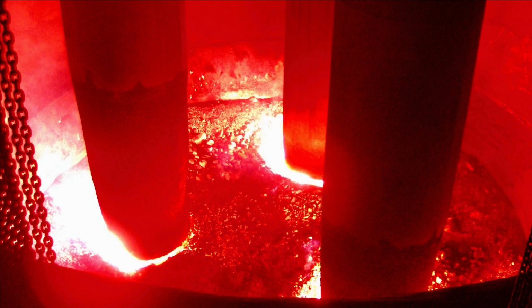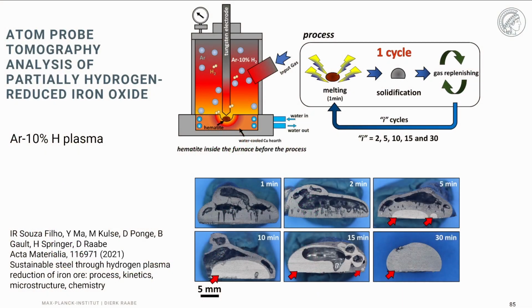Here you see these gigantic graphite electrodes that typically are used for melting down the scrap. But here we have built a little reactor where we do a very similar experiment. We flood the reactor chamber with argon and add about 10% of hydrogen gas. And then we ignite the plasma in the material, and we do it always for durations of 1 minute. Then we stop the processes, take the specimens out and test them regarding the iron content that was formed, put them back into the oven, flood the oven chamber with the same gas mixture and ignite the plasma again.